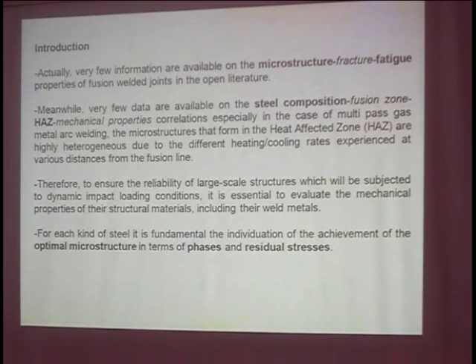In some cases in particular you can find very good data on just single experiments, just one steel in which few processing parameters are related to the mechanical properties or to the microstructural evolution, but a very broad conclusion cannot be drawn because there is not so much data available. In particular, the microstructure of fusion welds is strongly influenced by the properties of the heat-affected zone, which is directly related to the history of heating and cooling during the processing of fusion welds.